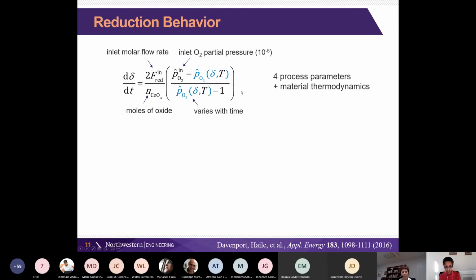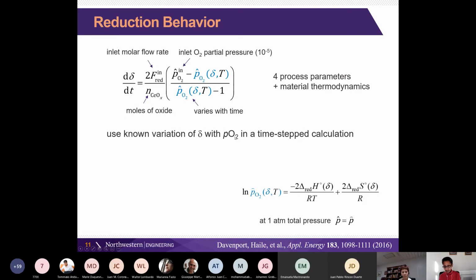So how are we going to use this? We're going to use our known variation of non-stoichiometry with oxygen partial pressure in a time step calculation. Very straightforward. This is what we evaluated previously in understanding our material. If our total pressure is 1 atmosphere, then partial pressure and pressure relative to the reference state are the same thing. So that makes the calculation straightforward.